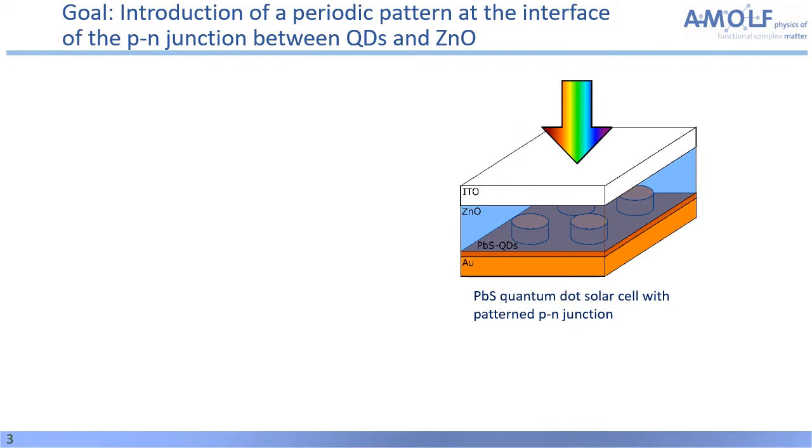What we aim for is to achieve this reduction of required absorber material by making the absorber layer itself resonant with light. Now, that would give you the structure you can see on the right, where you have quantum dot cylinders embedded in zinc oxide on some residual quantum dots at the bottom, and their dimensions will be chosen such that they maximize the absorption per unit volume in the absorber layer. This then will provide you with the benefits of having less material, so it will be cheaper, less toxic, and in this whole geometry you also don't need to introduce any new materials.